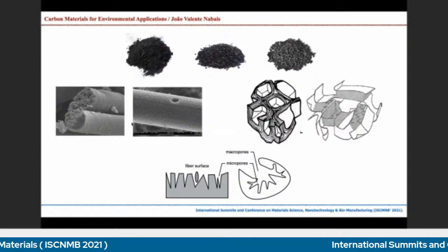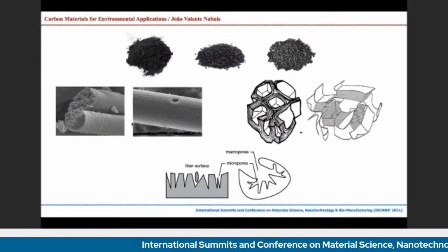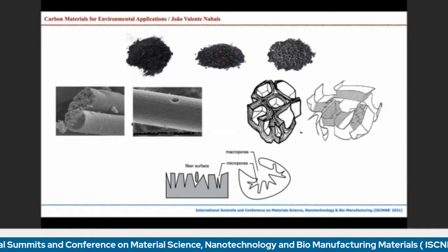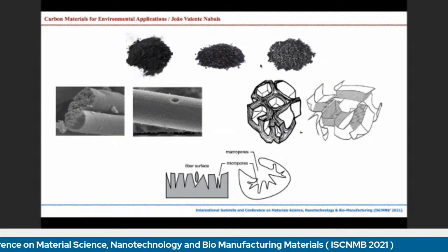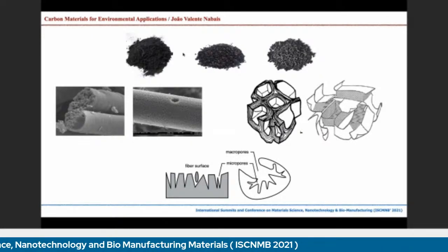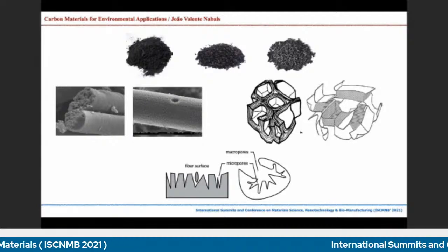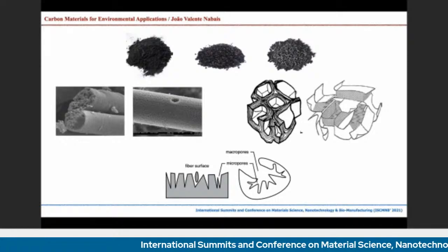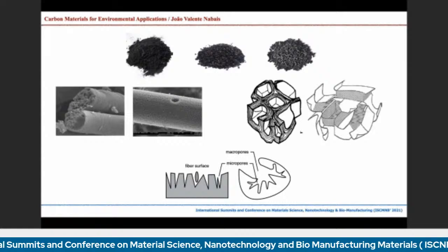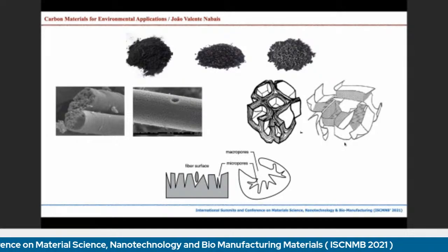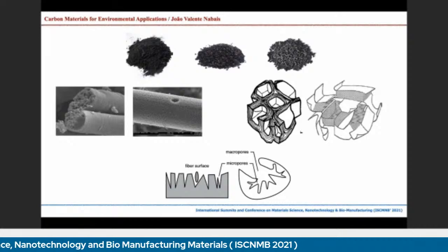We have 20 years of experience of producing carbon materials, mainly activated carbons and activated carbon fibers. You can see here on the top the physical forms of the materials. They can be in powder, granular, or in pellets. And this is the schematic structure of an activated carbon. Basically, it is a turbostratic structure filled with holes. These holes are the pores that the activated carbon has. This is a schematic structure.